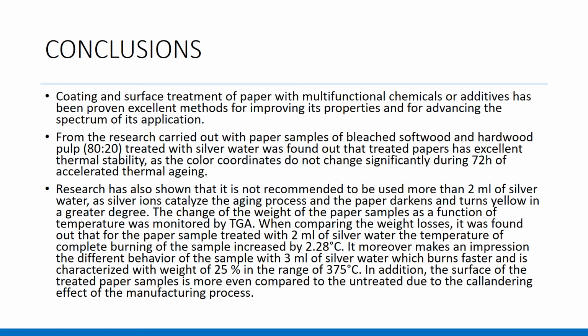The changes of the weight of the paper samples as a function of temperature were measured by TGA. When comparing the weight loss, it was found that for the paper samples treated with 2 milliliters of silver water, the temperature of complete burning of the sample increased by 2.28 degrees Celsius. It moreover makes an impression the different behavior of the sample with 3 milliliters of silver water, which burns faster and is characterized with weight loss of 25% in the range of